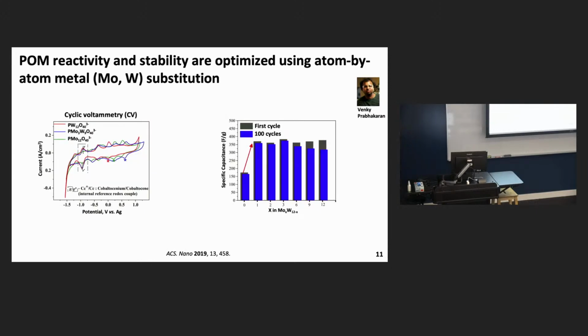So the results for energy storage are shown on the right-hand side, and the cyclic voltammogram is shown on the left. You can note there's quite different redox behavior depending on substitution of molybdenum atoms for tungsten. What's most surprising, though, is when you look at the specific capacitance, substitution of just a single molybdenum atom results in a drastically increased specific capacitance. I naively thought that this would be sort of a linear effect that you would see go up sequentially with the number of doped molybdenum atoms, but it's only really one that's necessary to give you almost the highest performance possible.